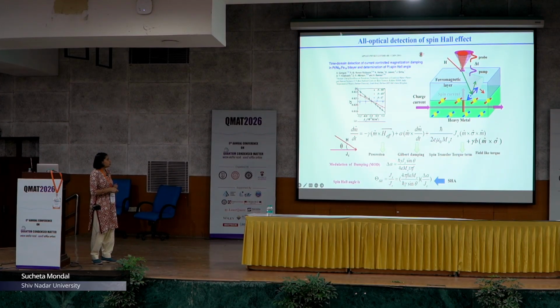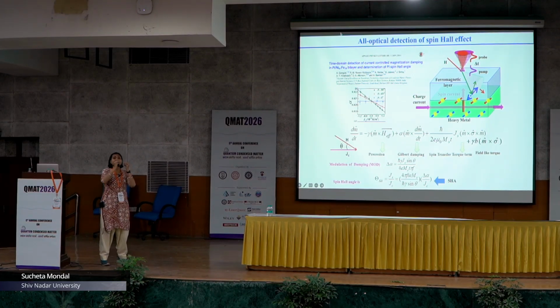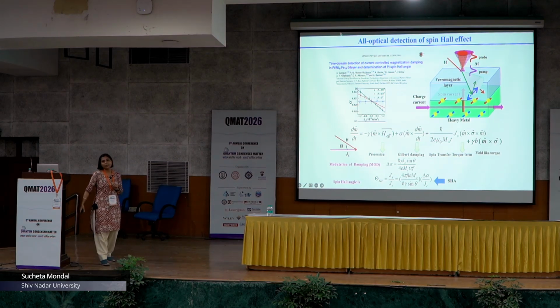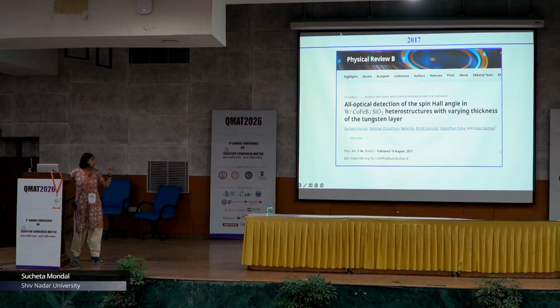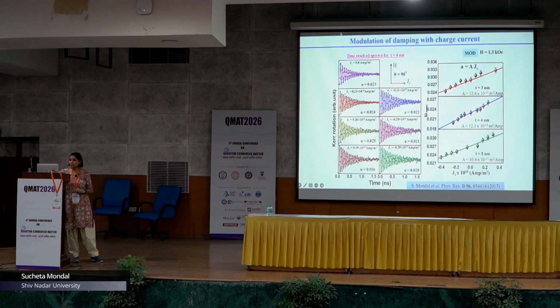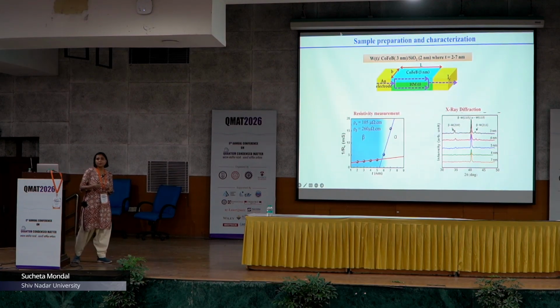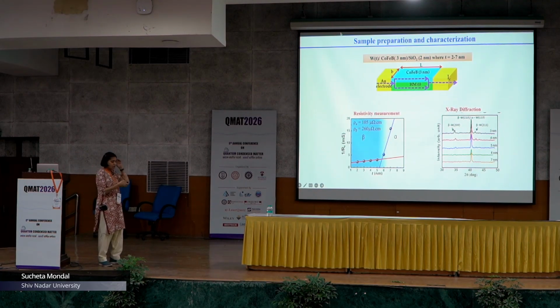After we found modulation of damping, which is delta alpha by Jc, where Jc is the density of the charge current and delta alpha is the change of damping of the adjacent ferromagnetic layer, then we can actually get the spin Hall angle from this formula. So in the first paper, which was my first paper in 2017, we studied tungsten, and we of course have observed a phase transition. Tungsten is known to exhibit phase transition in various conditions.